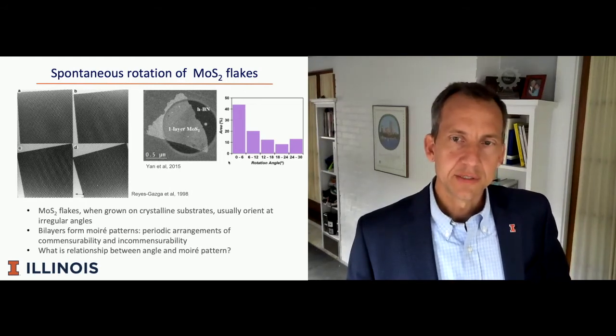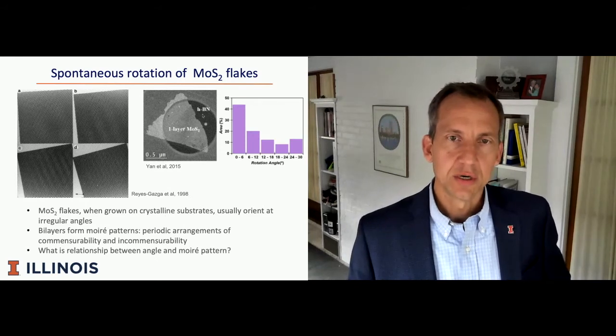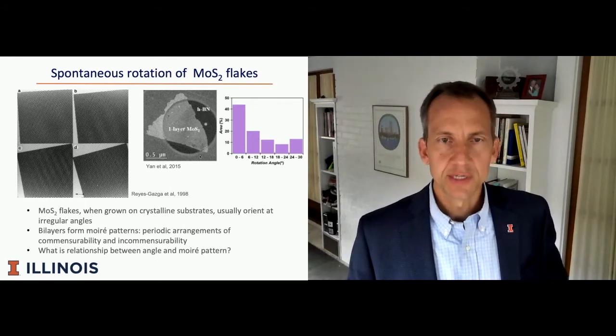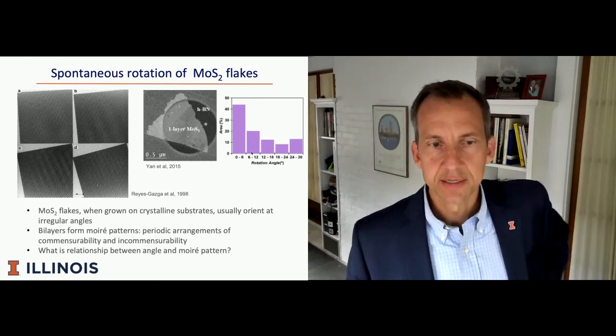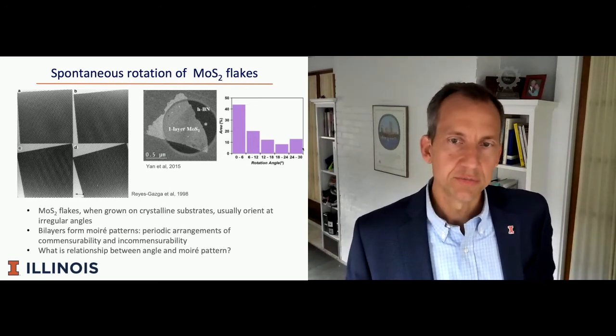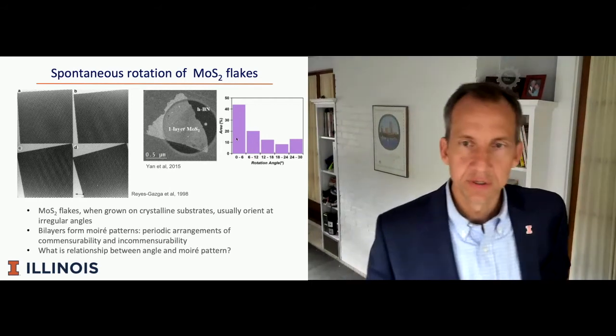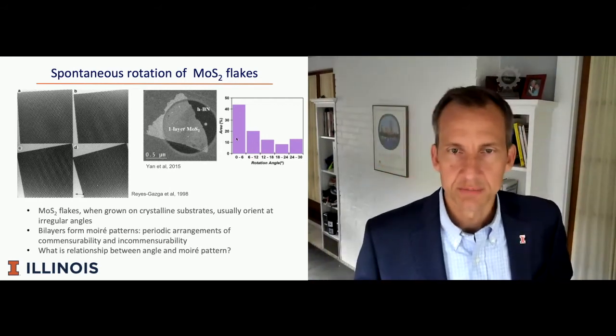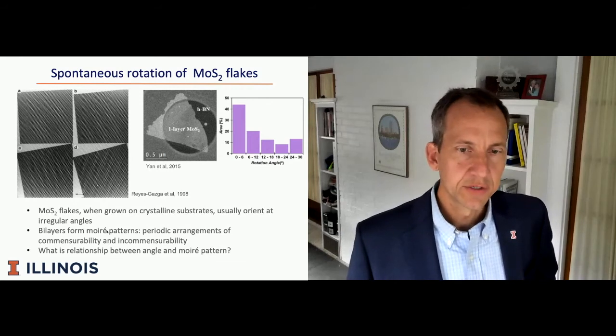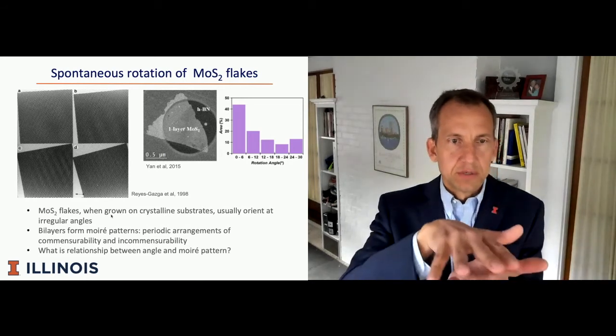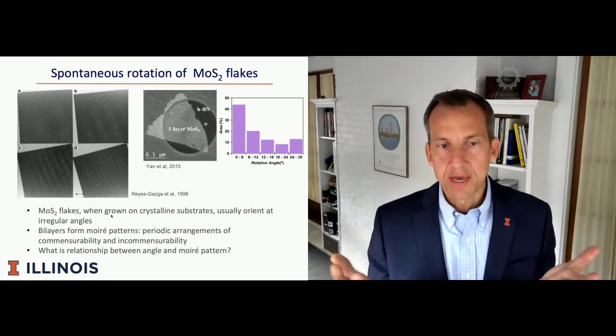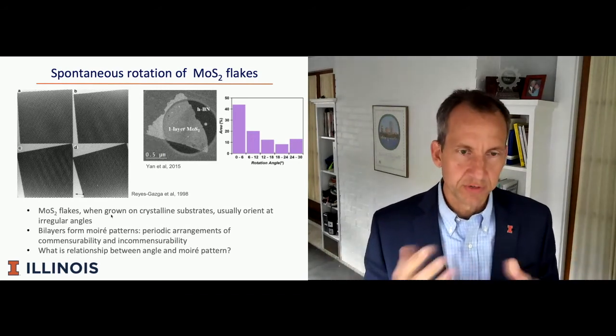On the right is a more recent observation of MoS2 on hexagonal boron nitride. And what's nice about this result is that it shows a statistical distribution of angles at which the top layer might situate relative to the bottom layer. And you can see that small angles are preferred, but many angles are possible. The other thing I wanted to show on this slide is more easily seen on the left-hand side, which is that when the bilayers rotate, they form moire patterns. And we know moire patterns sort of in our everyday life.